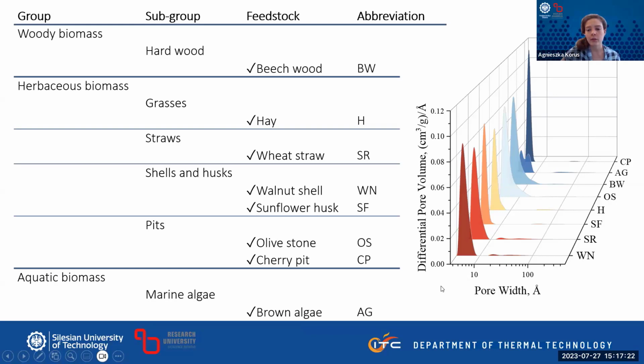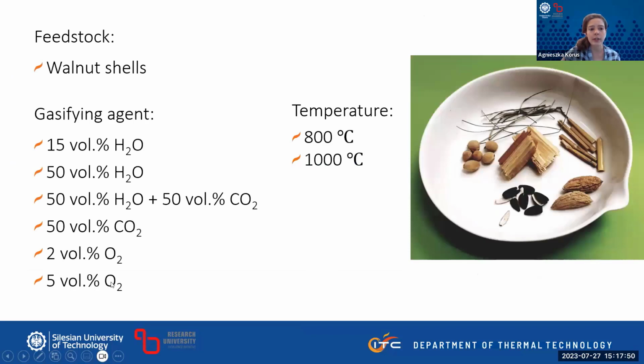For the main campaign, selecting the final gasification parameters, we used walnut shell biochar because the distribution was somewhere in between the most developed and the really bad ones. So we figured we could use it as a sort of average of our biomass chars. And we tested with different gasifying agents. Using nitrogen as a balance gas, we used lower and higher concentrations of steam. We tried steam with CO2, just CO2, and small amounts of oxygen. Most of the tests were carried out at 800 degrees Celsius. We did three tests with elevated temperature as well, just to see whether it would affect our pore distribution.